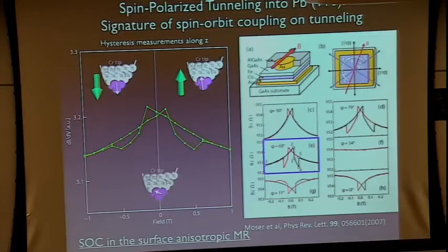Okay, and the challenge actually in these experiments is that often you find the tip that should be magnetic, should have magnetic contrast, and it has no contrast. So you have to really do these field measurements, you have to have a test structure. And our test structure is actually cobalt on copper, which makes these domains that are up or down. It's just like little bits you can read. You can test all these on it.